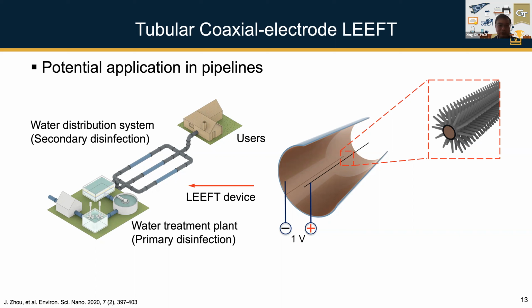So we already have the openings, and then we can potentially replace some of these sections with this tubular LEEFT treatment system. So what we can achieve is that we can provide secondary disinfection, right? One of the challenges for the current chlorine alternatives is that we can use UV or ozone in the primary water disinfection water treatment plants to replace chlorine. But in most cases, we still need to have residual chlorine in the water distribution systems to make sure the water is clean when it reaches the end users, right?